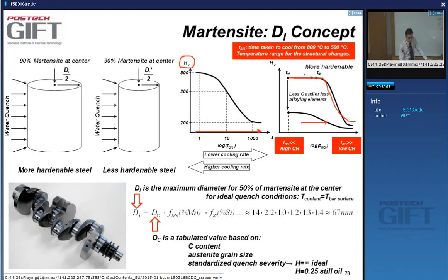Steels which have less carbon, for instance, or have less alloying elements, so are not as hardenable, will have S curves that look like this. So the data will look different, and you use it differently also in practice. But it's equivalent to this Jominy approach. Usually, if you want to use engineering steels, you need to have hardenability data available, which is usually published by the company that makes these engineering steels.